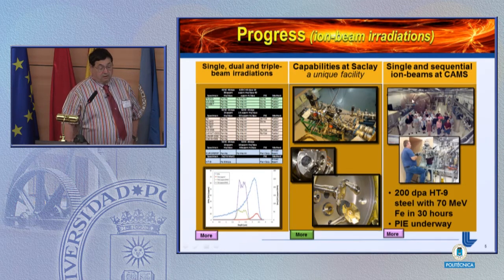Just some pictures of what goes on. This figure here is what our irradiations at Saclay look like. Here, this blue line is the displacement damage as a function of depth into the material. That's from a 24 MeV iron ion injected into an iron-based steel, iron chrome, or an ODS alloy. The red curve is the implanted iron ions, and these two curves, the rectangular shape, the large one is the protons that are being injected, and as you see, we use an absorber wheel to spread out the depth profile of the protons, and here's the corresponding helium.